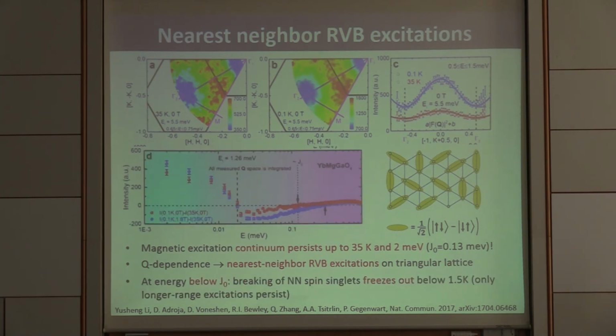And then we would expect that at low temperatures, we can't break the RVB states if the excitation energy falls below J0. And indeed, it is found that if we subtract from the low temperature intensity the high temperature intensity, it's getting negative below the energy scale of J0. And that means that the excitations below J0 have entirely different character, and they haven't been probed yet by inelastic neutron scattering. That's only a first glimpse. And here we really deal with a different type of excitation. And that determines the Pauli behavior of heat capacity, which was found below 1 Kelvin.